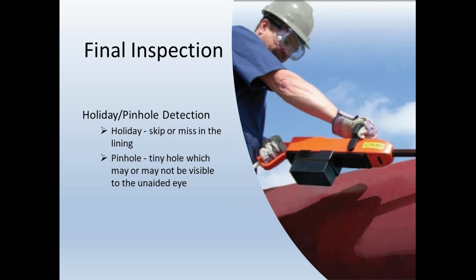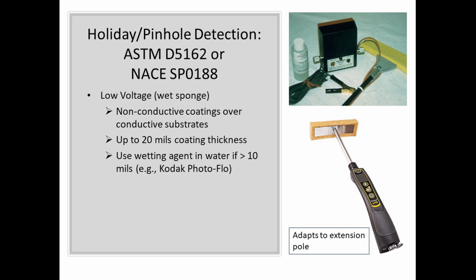Right? And then to finish this up here, I'm going to finish up really fast. Holidays and pinhole detection, we want to make sure that our lining system doesn't have pinholes and holidays in. A holiday's a skip or a miss. A pinhole's a tiny void, of course, because that could end up with product contamination, corrosion, and so forth. So we can either do low voltage or high voltage holiday detection. Low voltage is typically less than 20 mils. High voltage is typically over 20 mils.